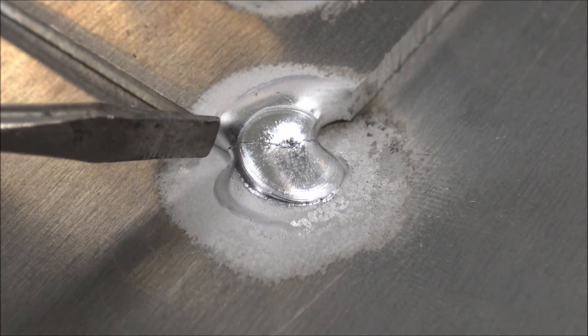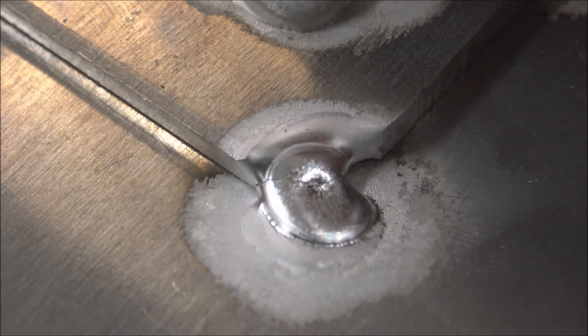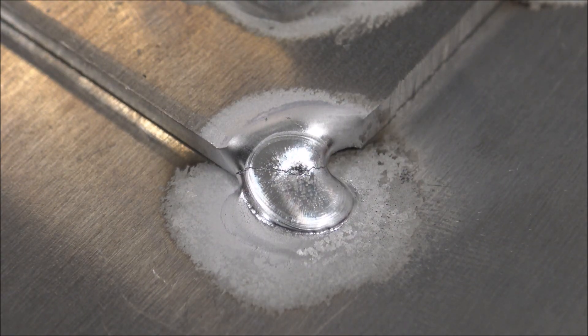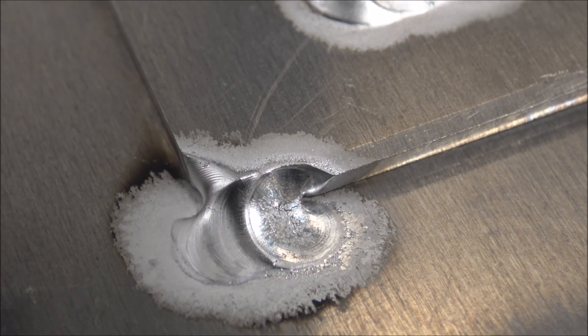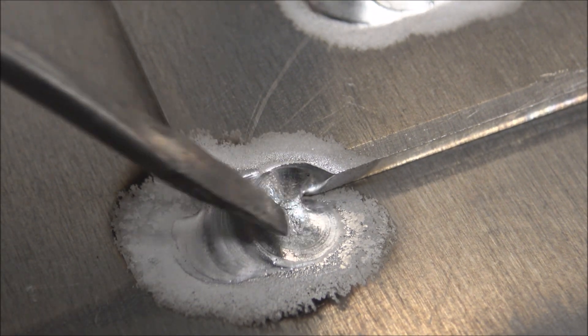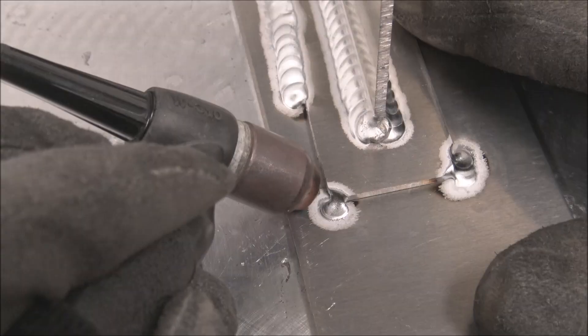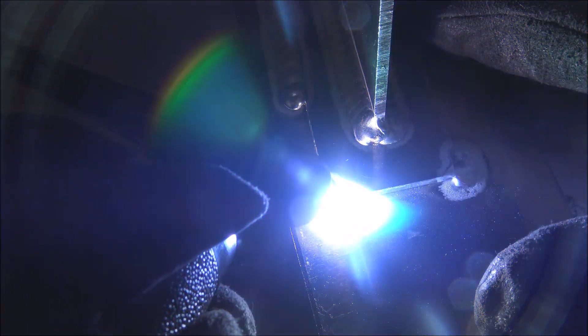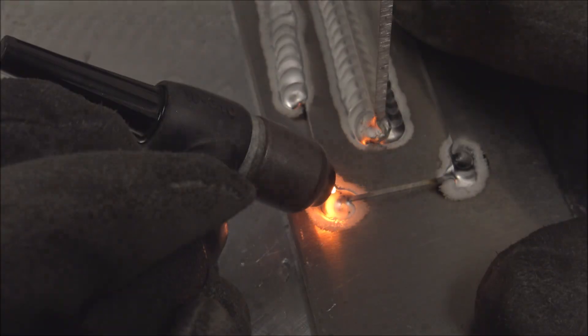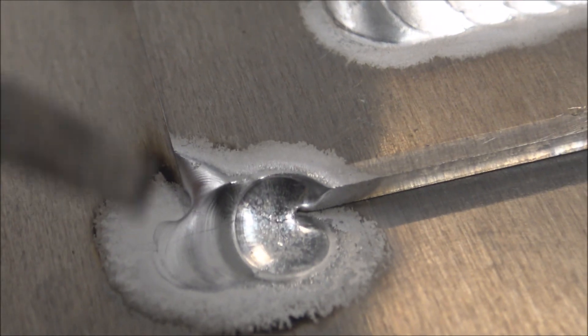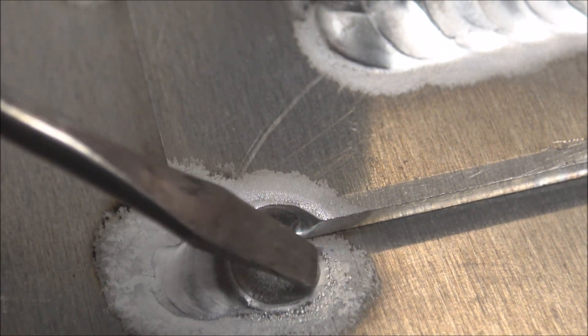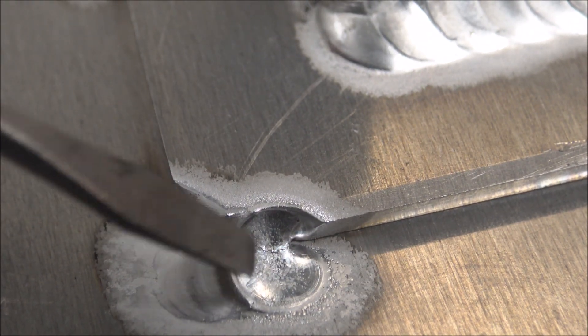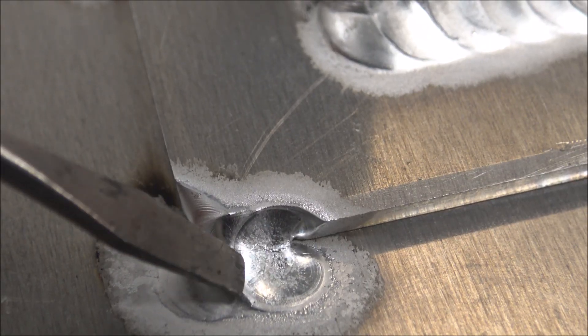See how that one split? It was still holding together a little bit. But to fix this, all you've got to do is just come in and get a little bit more surface area fused. You don't go twice the width. If you look real close, you can see that one's cracking too at the end there. But that's fine. You just come back on your start. Liquefy it. Come back. Make sure you come back past the crack plenty. Dab some rod and then get going.